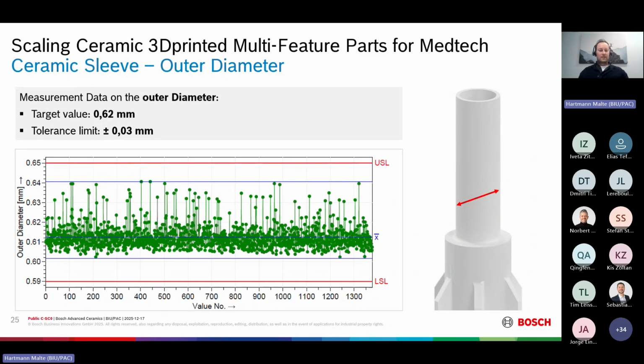Another feature here is the outer diameter. The target value here was 0.62 millimeters, and we see here all values are within specification. 2 of those values of the 1,400 are on the process capability limit. So we see more variation to bigger size due to slight overpolymerization on the outside diameter, but they are still within limits. So actually this feature could just be tested by random sample testing.